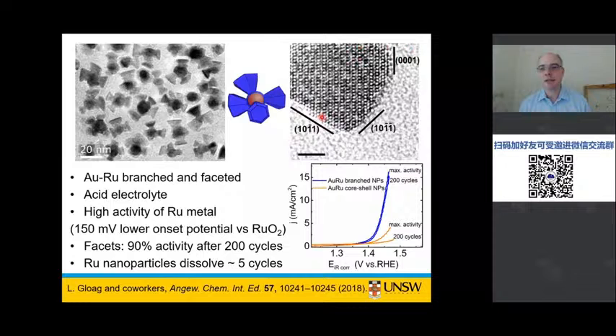And then we can do our high resolution electron microscopy of these particles. And we can look at the high resolution image. So we have all this beautiful atomic resolution where we can see the atoms. And then we can index these surface facets to identify them and see what we have. And as you can see, we were very pleased that when we did this synthesis, we actually ended up with ruthenium branch nanoparticles with the low index facets that we're after. So these facets that have ones and zeros in them.